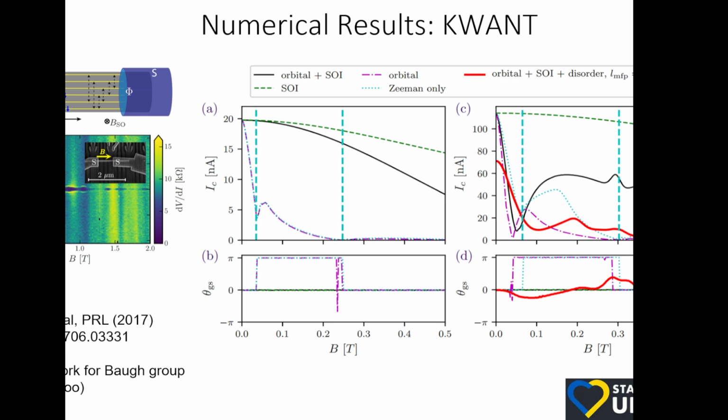So in a cross-section like this, there'll be thousands of modes. But in a semiconductor, there are 1,000 times fewer electrons. Every 1,000th atom contributes a conducting electron. So the density is a lot lower, and also effective mass is very small, about 100th of an electron mass in free space, right? So in this material, an electron can occupy the entire 100 nanometers of this wire and really present itself as a quantized mode in the entire cross-section.